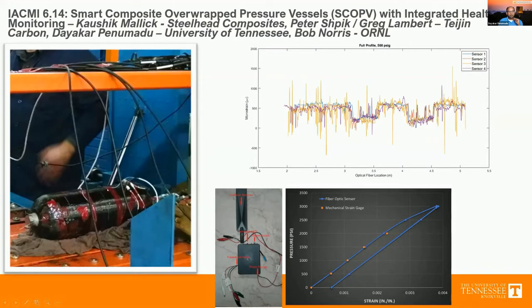on top of which this carbon fiber tow-preg was wrapped, and we were able to monitor the strains at various locations through the thickness along the entire length of these fiber optic sensors. What you see very nicely here is something you would miss if you were to use traditional foil gauge sensors or strain gauges, because in between adjoining tow-pregs, or infused wet tow-pregs for the wet filament winding process, there are strain concentrations in the resin-rich region. As you are load testing this to burst capacity, you get very, very high strain localizations that we were able to capture with this technology, which has never been done before.